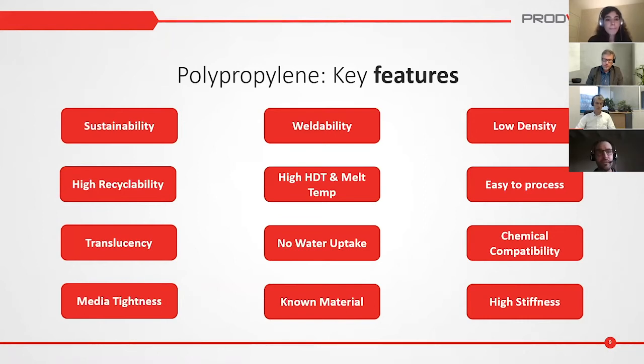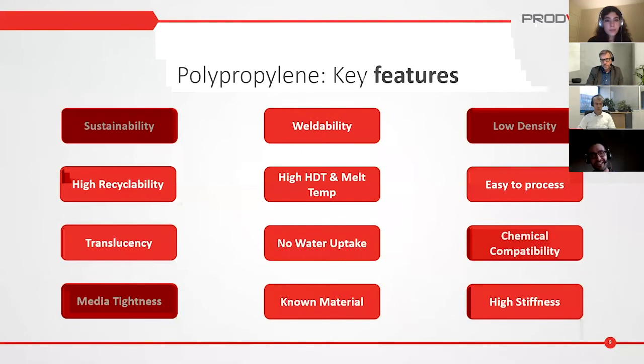The weldability, I've talked a bit about it. We have tested around 10 different welding methods, and all work just fine, as they do with traditional PP. Often the welded area of the part is not even the most fragile area in the part. The lower density is also quite a nice feature, and it is true for PP. PP is the plastic with the lowest density of all, and this is also true for 3D printed polypropylene. This can make this material particularly relevant for transportation applications where weight or lightness is a key topic. Also, as a consequence, you can fill up your machine with fewer kilograms, so it also drives the cost down a bit.